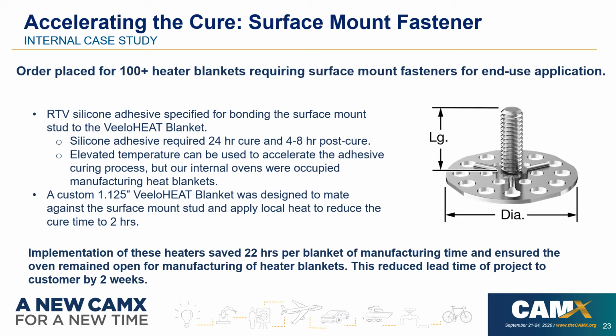The supplier recommendation for the adhesive is a 24-hour cure, and then a 4 to 8 hour post cure for this adhesive. Using elevated temperatures, we were able to accelerate the adhesive curing process.